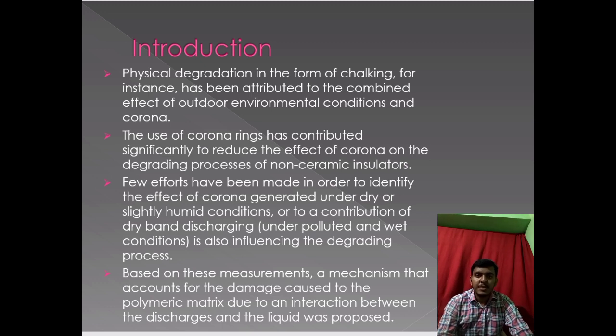Even if new materials with enhanced electrical properties are available, as long as the insulator is subjected to the high voltage, the influence of corona on mechanisms of degradation of dielectric material cannot be completely eliminated. Until now, only few efforts have been made to identify whether degradation observed at the energized end of a polymeric insulator is due to the effect of corona influencing the degradation process. In polymers having intrinsic highly hydrophobic properties, such as EPDM and silicon rubber, deposition of surface charge has been identified as a factor leading to the temporary loss of hydrophobicity.